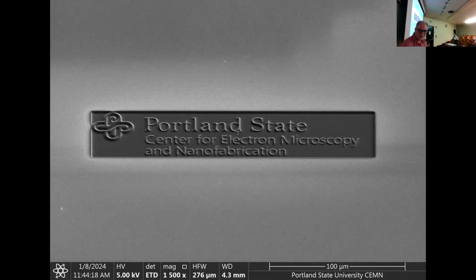If you look at the actual PSU logo itself, you can see it looks kind of rounded. I think it has a neat artistic effect. A lot of that rounding comes from all of those weird grayscales that are thrown in, and also the fact that the beam was a little bit fat for this application. I did this at 15 nanoamp, so I had a pretty fat beam, and plasma FIB beam distribution is somewhat Gaussian. So you're going to be doing some milling with the tails, which is going to make matters a little bit worse. And the higher your current, the more tail you have hanging out there.